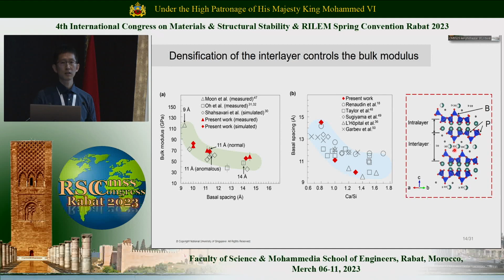The novelty of this work is that it provides the very first direct experimental measurements of the anisotropic incompressibility of CSH along all different directions, and how that changes when you change the configuration, the crystal structure, of the nanocrystalline CSH. This result can be directly used to validate the molecular dynamic simulation, and can be used as an input value for a bottom-up homogenization scheme.